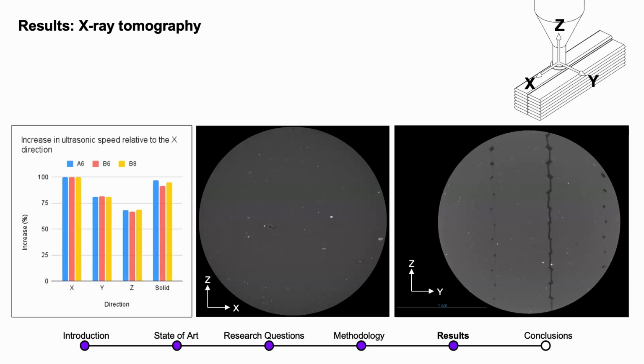It's logical to think that the ultrasonic speed in this direction is faster than in this one, the Y direction, because the sonic wave will find this crack in its way. But it's strange that in the Z direction, which is this way, in the tomography we find a very homogeneous material, but it's the slowest one.